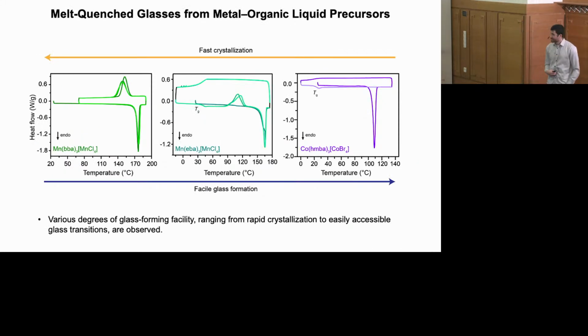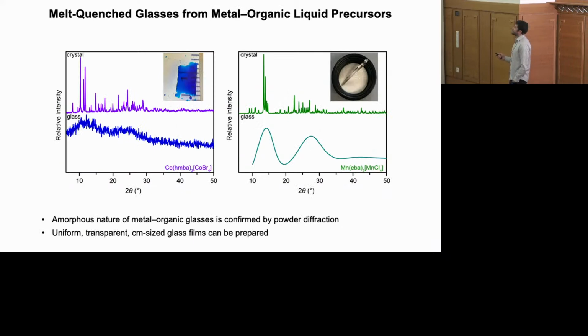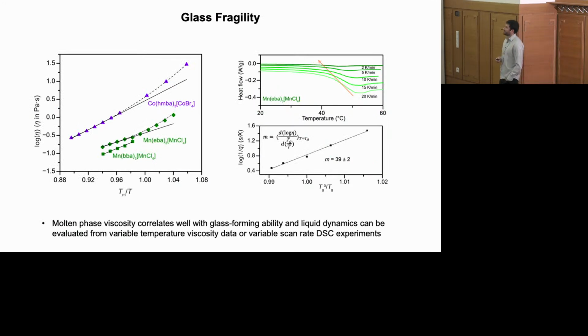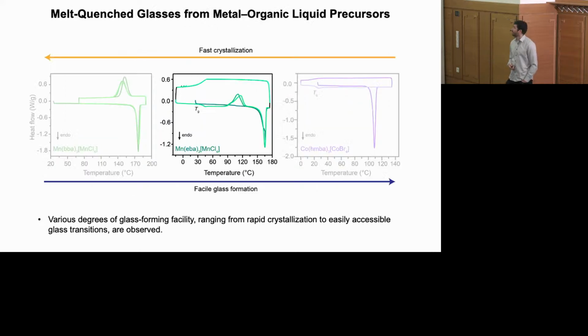And so I'll start to wrap up by saying we can access a very wide regime of different rates of glass formation in these kinds of materials, making materials that are very excellent glass formers to poor glass formers and everything in between as well. And we can characterize these glasses using X-ray diffraction-based techniques, and we can also synthesize really large, transparent, high-quality glass films of a lot of these materials, and evaluate a lot of different glass physics type properties about these systems. What's particularly exciting about having this kind of wide tunability in manipulating these glass transitions is that we can get to regimes where we can make materials that will undergo a transition from a liquid to a glass, and then upon heating can be recrystallized back into the crystalline state.